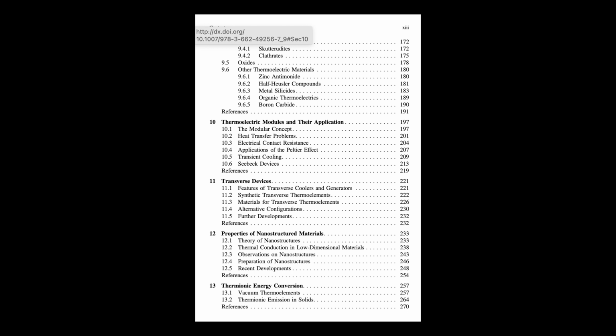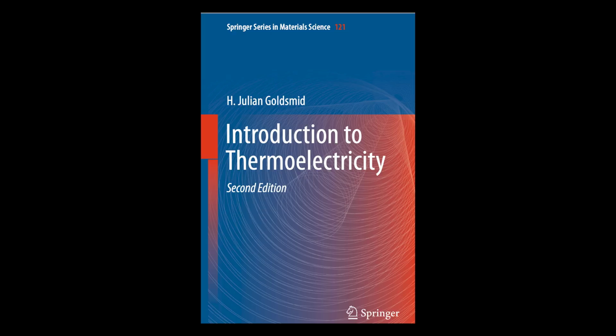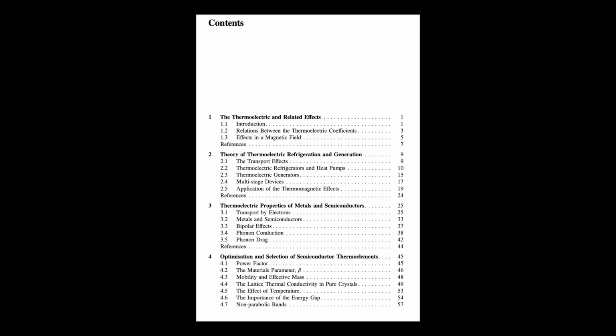Okay, now, the outline also mentioned thermomagnetic effects. Nernst and Ettingshausen, how do they fit in? Right, these are effects that pop up when you have a magnetic field involved as well. Take the Nernst effect. If you have a temperature gradient along a material, and you apply a magnetic field perpendicular to that, you can get a voltage appearing across the material, perpendicular to both the heat flow and the magnetic field. And interestingly, the sign of this Nernst voltage doesn't care if the charge carriers are positive or negative, unlike the Hall effect.